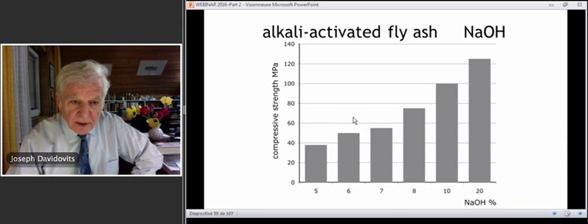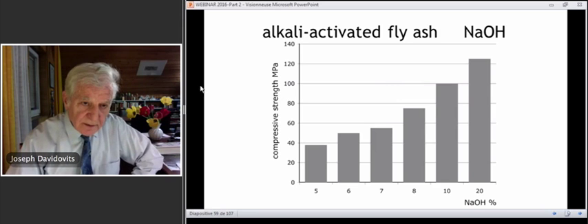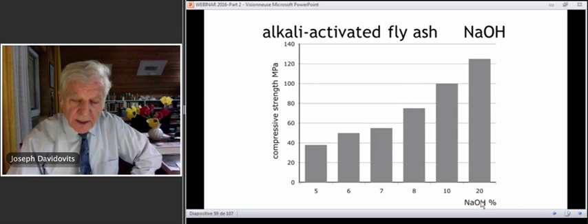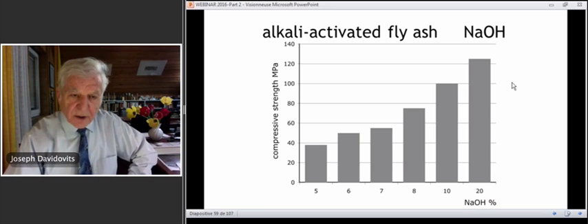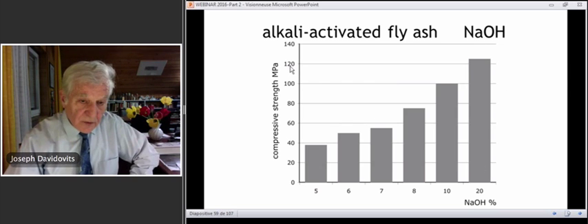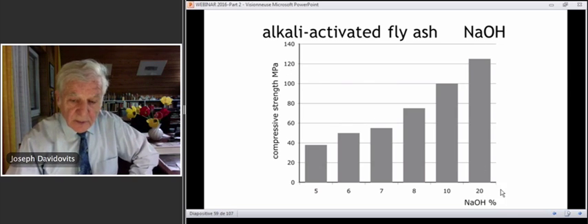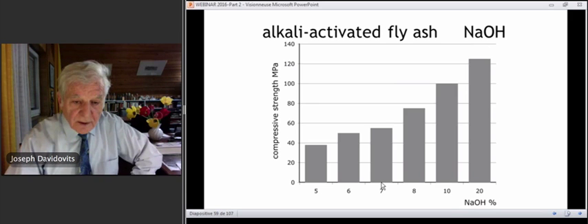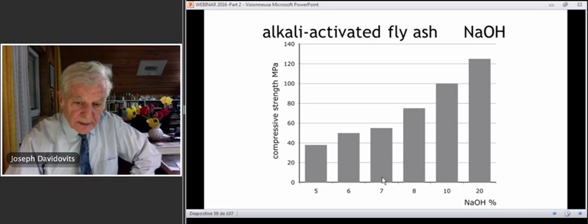As a result, in order to get high strength, you need more and more NaOH. Otherwise, you don't have high strength. You don't have enough matrix at your disposal. You have to destroy the entire spheres before having a good matrix. And so, if you want to reach 120 MPa, you must add up to 20% or more NaOH in your system. Crazy. Usually people stop by adding 7% because it is still super caustic and they get 50 MPa.